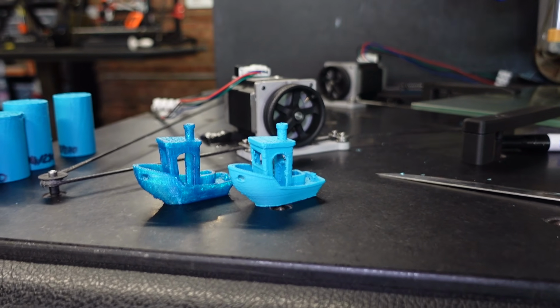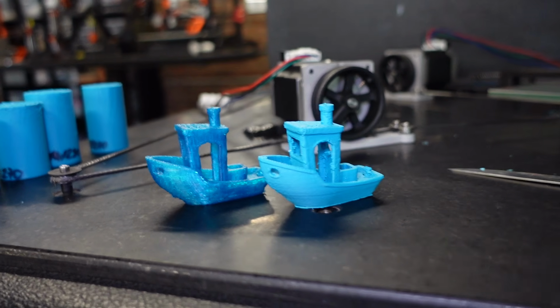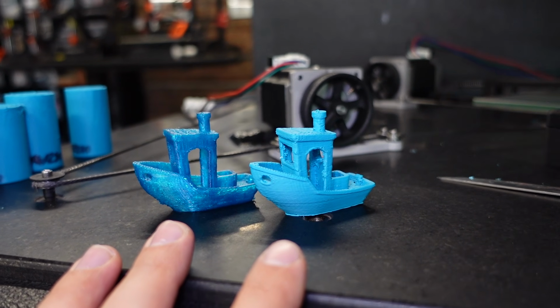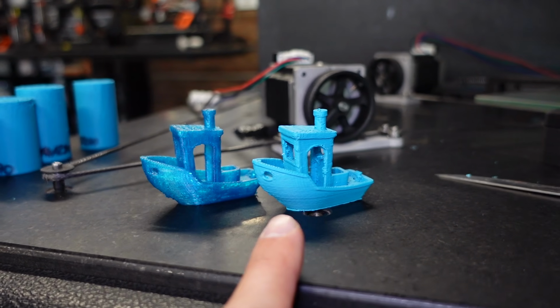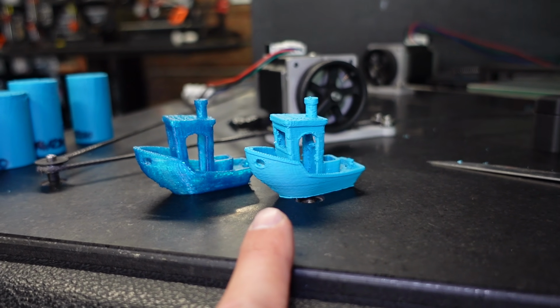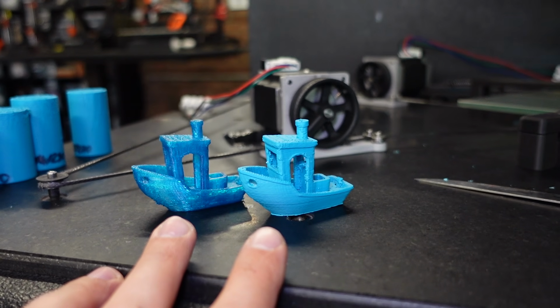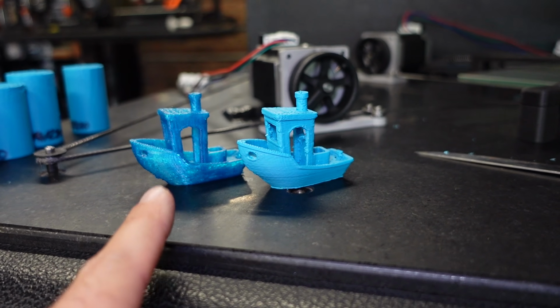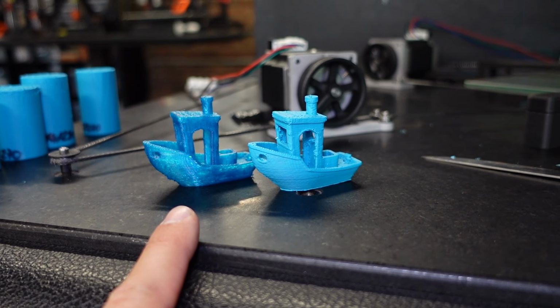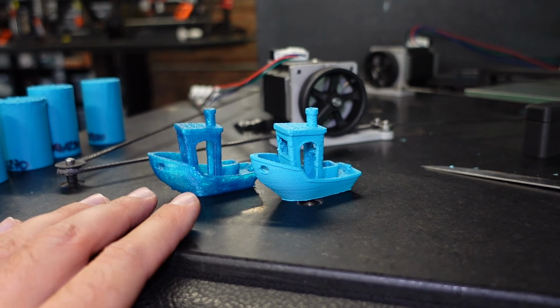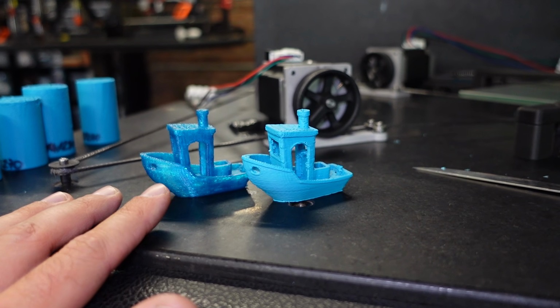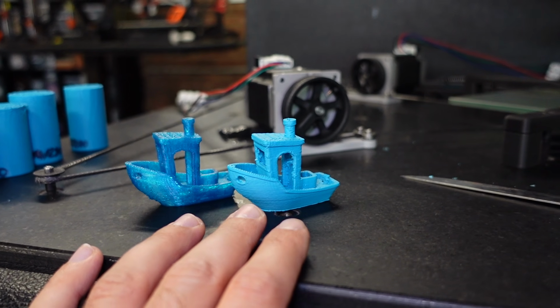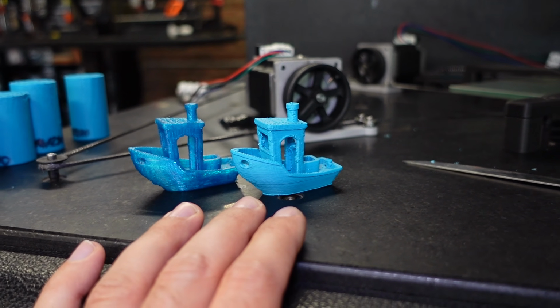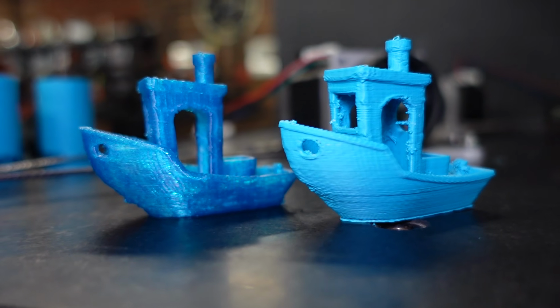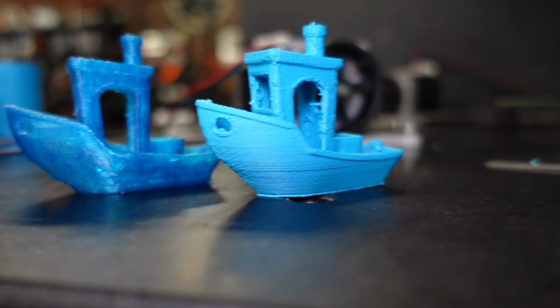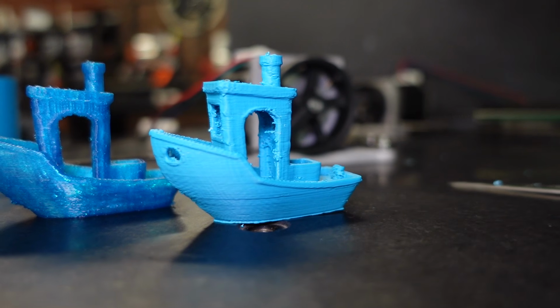Alright, let's talk about ABS for a second. This is pretty much apples to apples comparison. This is PLA, this is ABS, both printed around 3 minutes 20. Keep in mind with the same code. So the code is pretty old essentially. For a few months I've been using the same reference profile. Nothing has changed, nothing is optimized, and now ABS also has to take a go with it. So as you can see, this does show a lot of potential if you see over these little boogers.